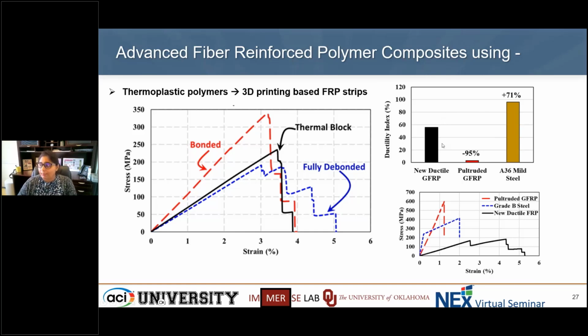but the new design approach can maybe get that GFRP into becoming more ductile and maybe comparable to that A36 mild steel. So this is a comparison between stress versus strain. You see this pultruded GFRP, which is highly linear elastic to failure, very strong, with good stiffness. You see the steel, which has a reasonable yield strength with high stiffness. And here is the new GFRP with those orientations and altered bond, achieving lower stiffness and strength, but very high ductility index compared to a pultruded GFRP.